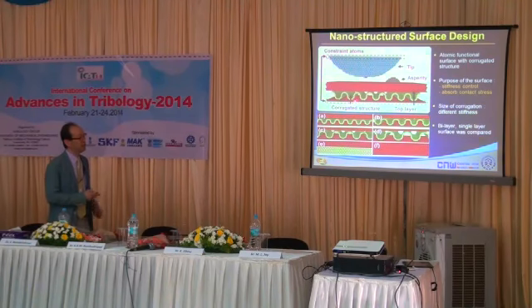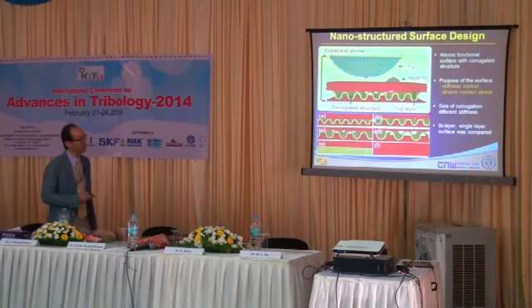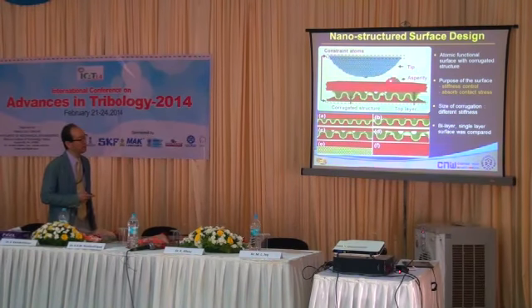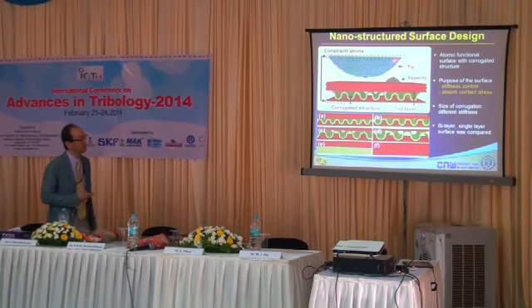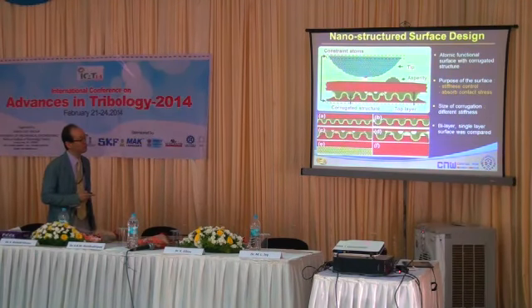And what you're looking at here is a corrugated surface with different geometry. And on top of that, you have another coating layer, and I put an asperity there. And there's a tip. What we're going to look at is what will happen when the tip approaches the surface, contacts it, and slides against the asperity, and how much wear will occur on the tip. This is what we want to see.